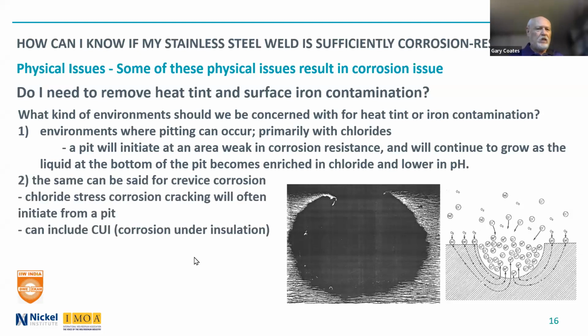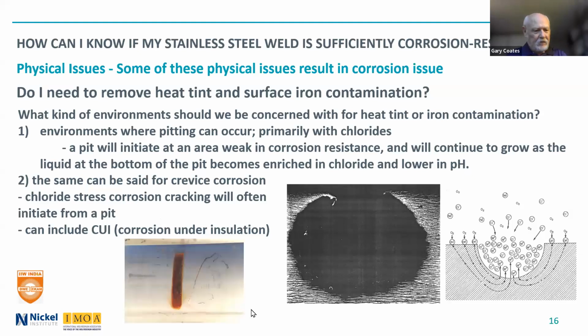Same can be said with crevice corrosion. Crevice corrosion is the same sort of mechanism, and that's why we talk about the issues of start-stop defects. You might have a crevice with intermittent welds, you might have a crevice without full penetration. And from an outside point of view, corrosion under insulation. So if that pipe that had the rusting from the strapping on it, you insulate it because let's say it was carrying some hot liquid or steam inside, that area will be the first one to suffer corrosion under insulation, that pipe there.